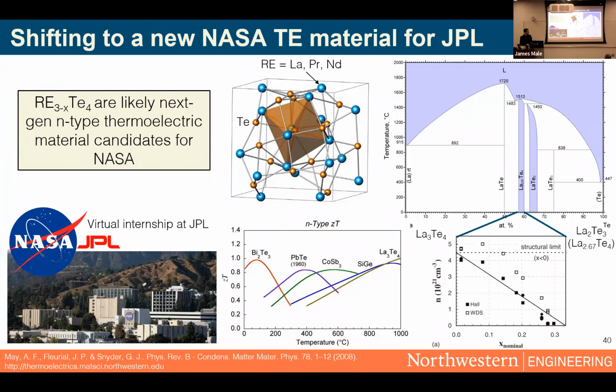Now, the thing I find most interesting about this material class is the ability to accommodate vacancies in the cation site. You might recall I showed you a lead telluride phase diagram earlier that was super, super narrow, and you had to zoom in to see the phase width. In these 3-4 structure type rare earth telluride materials, you actually see the phase width without even zooming in. So it can accommodate tons of vacancies without actually changing its phase.